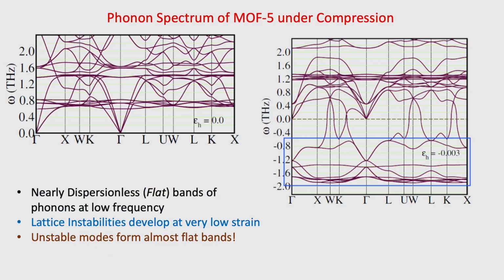So what we will do is we will basically start with phonon description again. As I motivated, it is relevant to both flexibility and amorphization. On the left is a phonon dispersion of the equilibrium structure of MOF5, and the moment you compress it, even by very little amount, it develops many unstable modes. And not only are these modes unstable, they are essentially very weakly dispersed, meaning their frequency doesn't depend much on the wavelength. And what this means is you can have basically unstable distortions or energy-stabilizing distortions at any length scale and give disorder in the crystal.